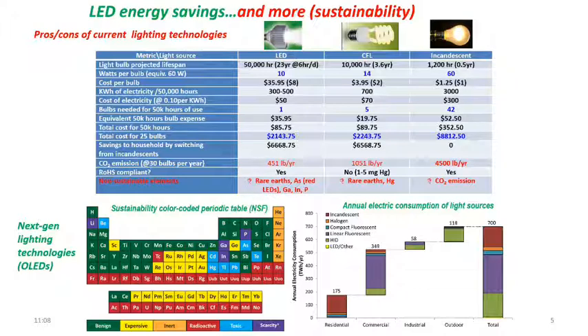The mercury will only give you UV light. Mercury light emission will be in the UV. But to convert it to white light, they have to add to the glass, in addition to the white matrix, which is barium, aluminum, something else in it. It's pretty cheap, but they dope small amounts of rare earth ions. So typically, europium in the +3 oxidation state gives you red, and in the +2 oxidation state gives you blue, whereas the green you get from terbium in the +3 oxidation state. So the LEDs utilize gallium nitride, and that gives you blue light instead of UV light.